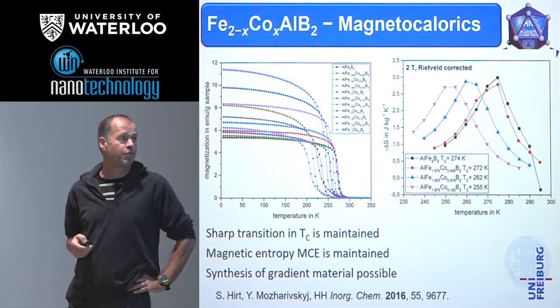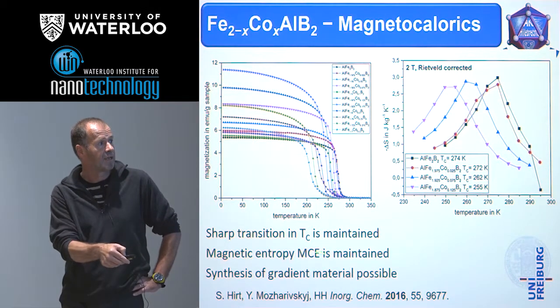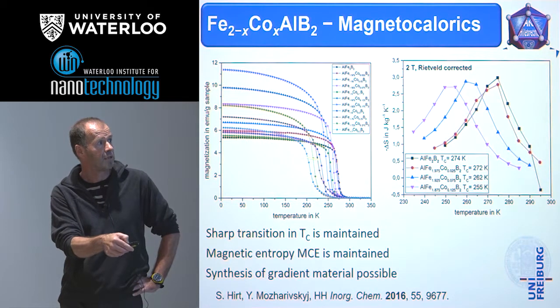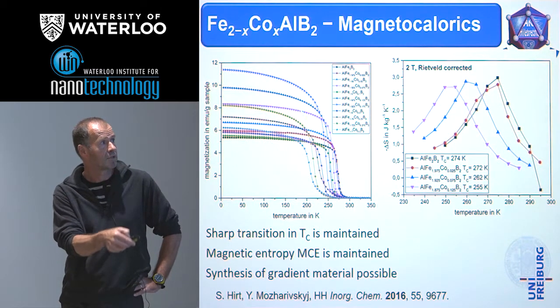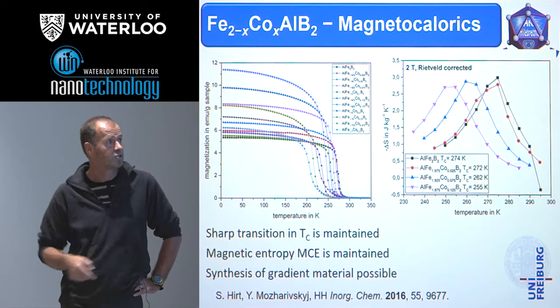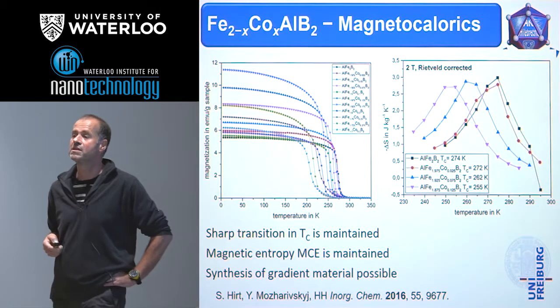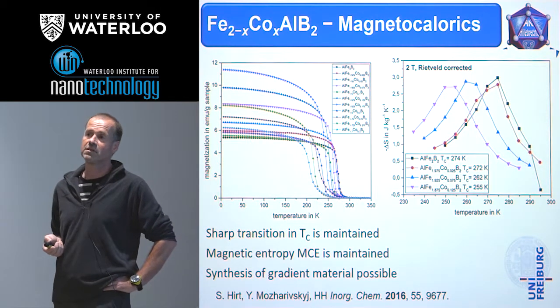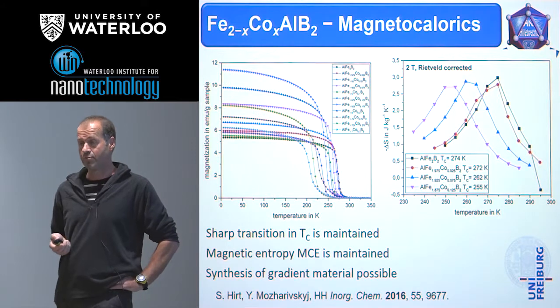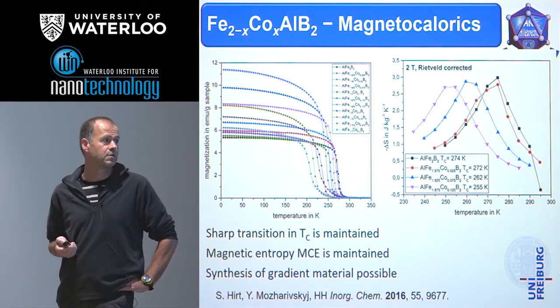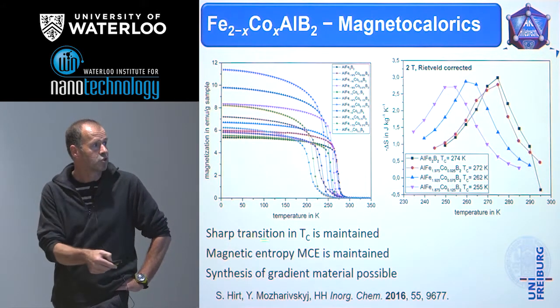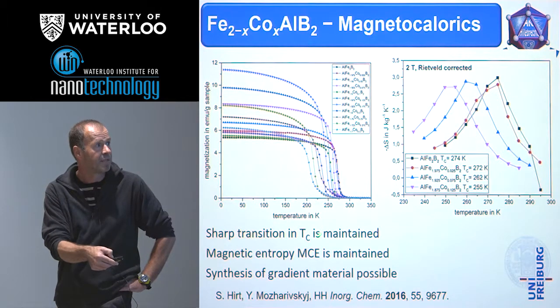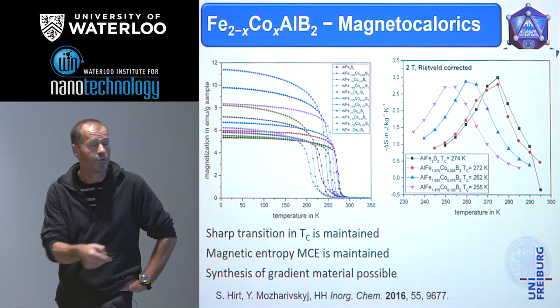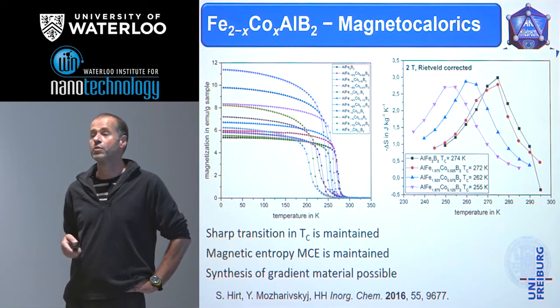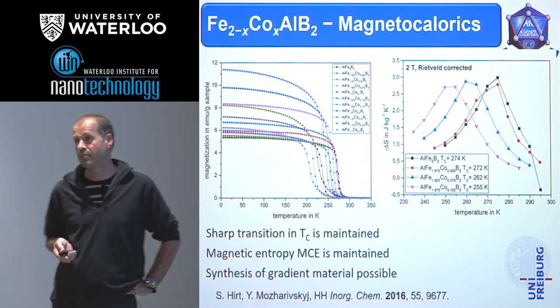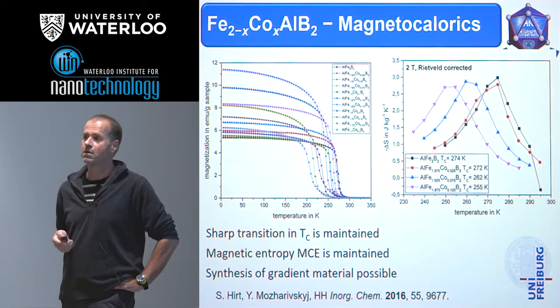We could show that the magnetic entropy is more or less maintained, and the different size is just a different amount of the sample. That means the entropy for the process is nearly comparable for all different cobalt contents, and we also could show that the sharp transition is maintained for all the compositions. So we have a new material for application in magnetocalorics.